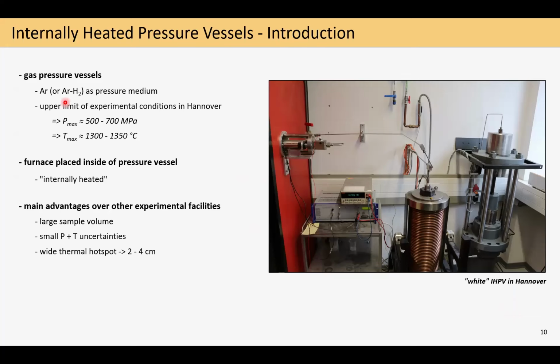Well, it is a so-called gas pressure vessel, meaning that we are using argon or a mixture of argon and hydrogen as pressure medium. And although the upper limits of experimental conditions vary quite a lot among the different labs, I'm just showing here the conditions we are currently capable of reaching in Hannover, which are pressures in the range of 500 to 700 megapascal and temperatures around 1300-ish degrees. And the name internally heated comes from the fact that the furnace, so the heating system itself, is placed inside of the vessel and thus also under pressure during the experiment.